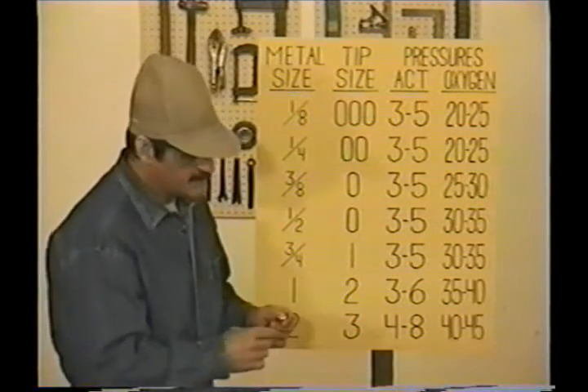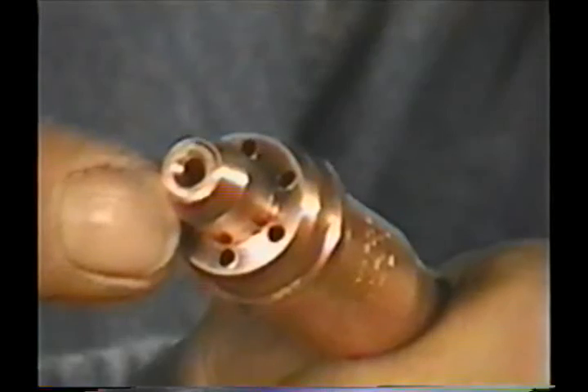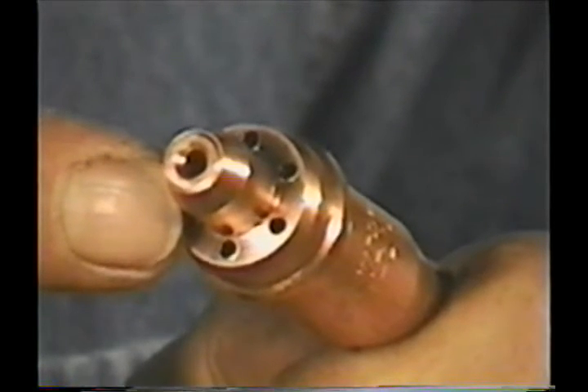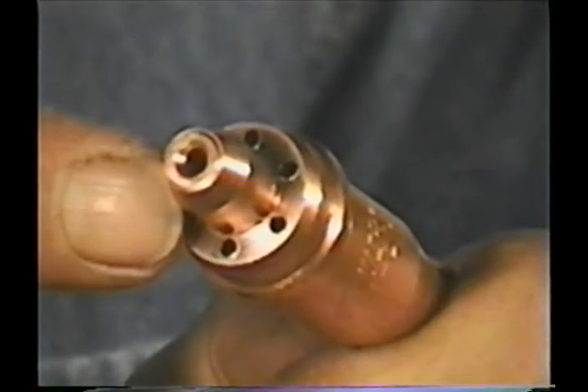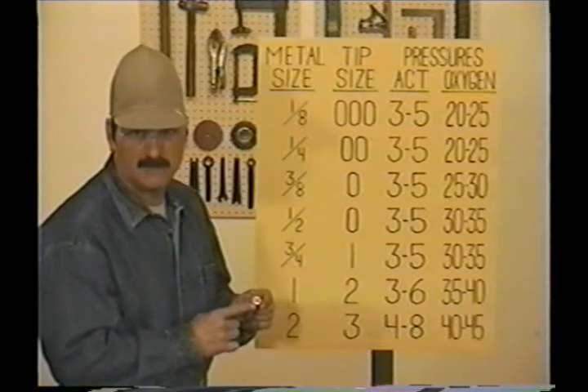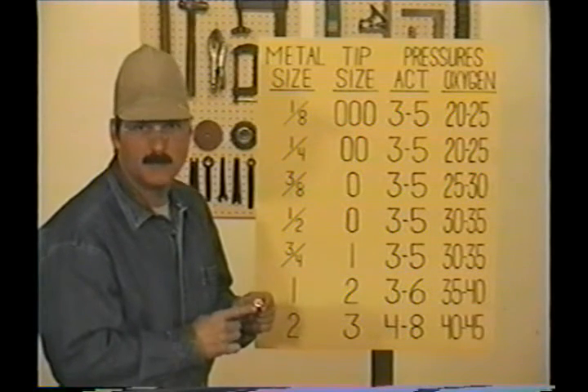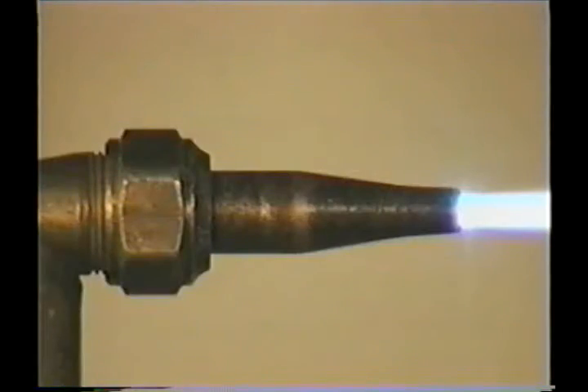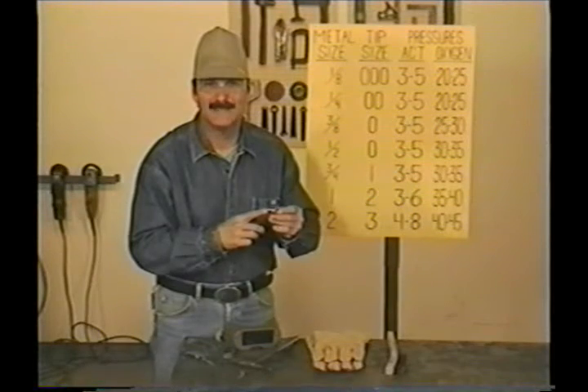Now, these tips seal to the cutting head on this back surface, so you want to protect this from getting nicked or scratched. If you do get a leak there, the torch will make a steady popping sound. And you need to replace the tip.